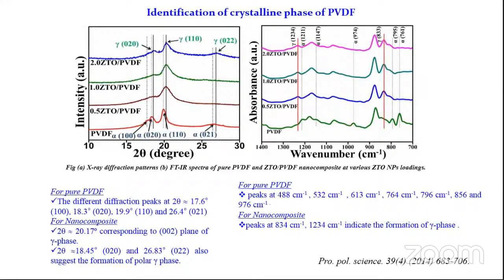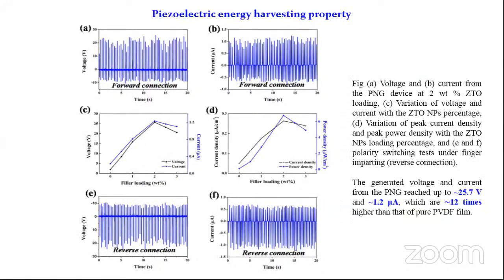This can also be proved from the FTIR spectra of the composite. In the FTIR spectra, the peaks at 834 and 1234 centimeter inverse indicate the formation of gamma phase in the PVDF ZTO nanocomposite. This is the piezoelectric output performance, as I said before. After fabricating the piezoelectric nanogenerator, we have got a maximum output voltage of 25.7 volt and a maximum output current of 1.2 microampere, which is 12 times higher than pure PVDF. Compared to the previous two reports, we have found that only at a small amount of ZTO loading, we got that amount of voltage and current.